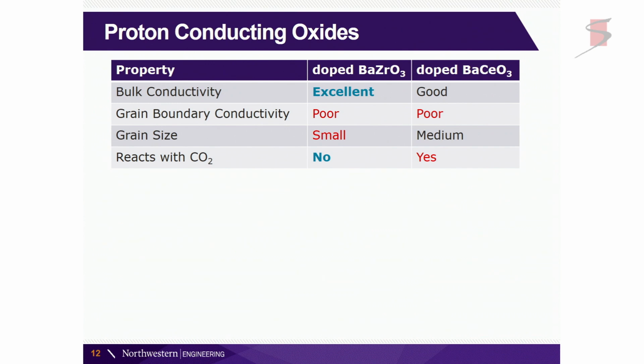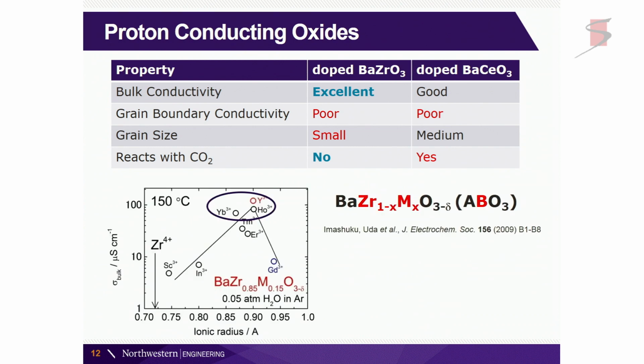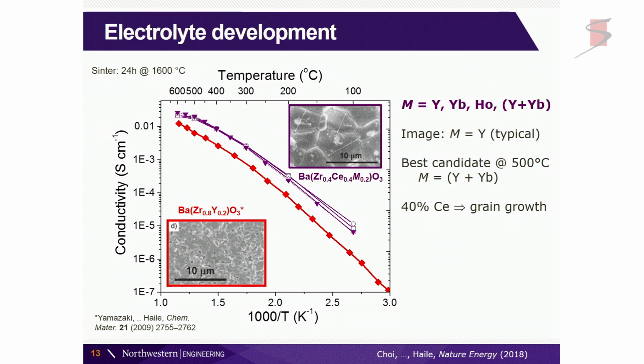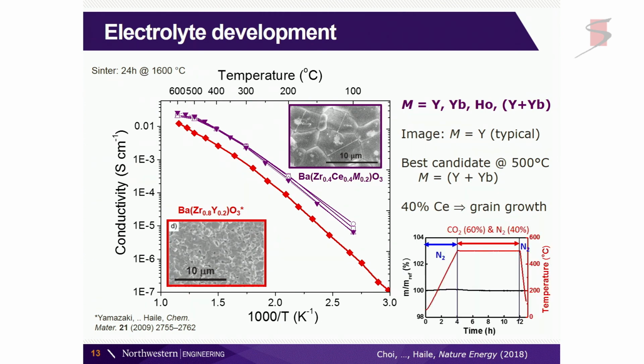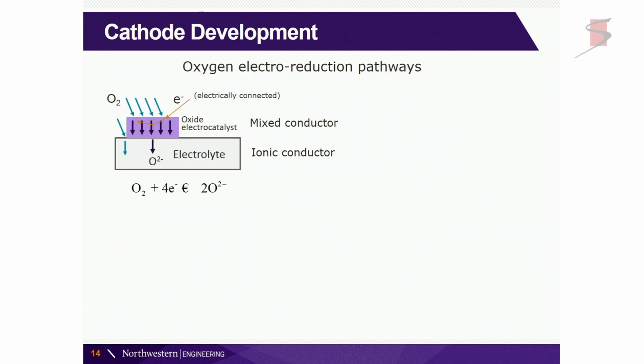So, coming up with a better electrolyte, we looked at these materials. I mentioned the doped barium zirconate. This is a perovskite, and there's a doped barium cerate, and there are trade-offs between these two. The straightforward thing to do is to look at intermediates. But as we do that, let's think about what kind of dopant we would use. So these are the good choices of dopants. We looked at these intermediates using these materials as dopants, and we developed some new electrolytes that had somewhat higher conductivity than this hard-to-process material. We did establish that it's not reactive with CO2 because we put it in a CO2 environment at high temperature, and there's no mass gain. So we have a nice electrolyte. We can move forward.